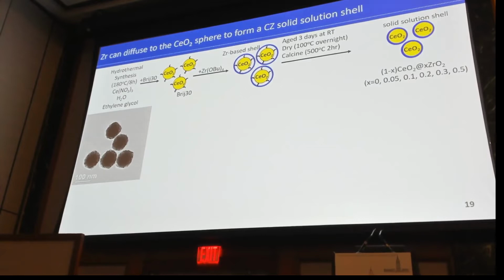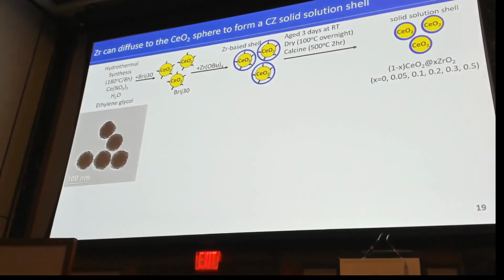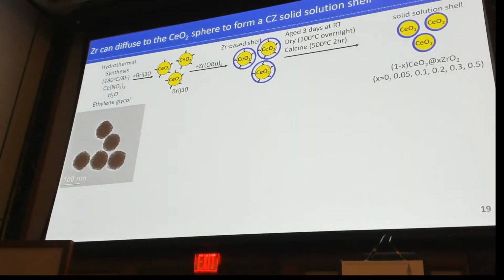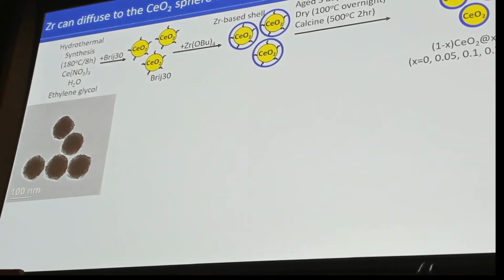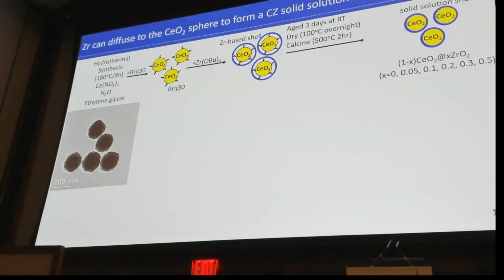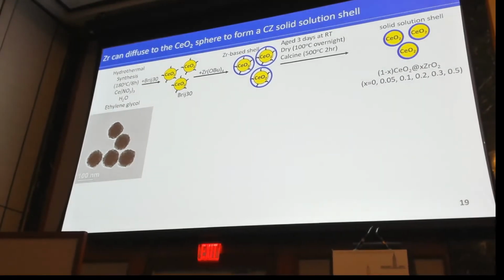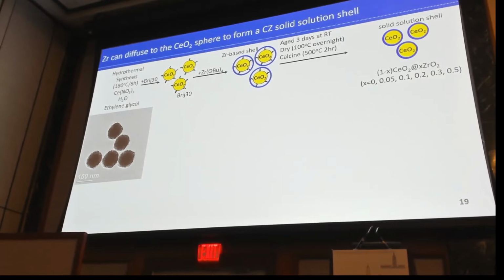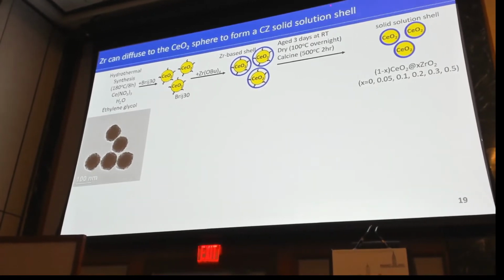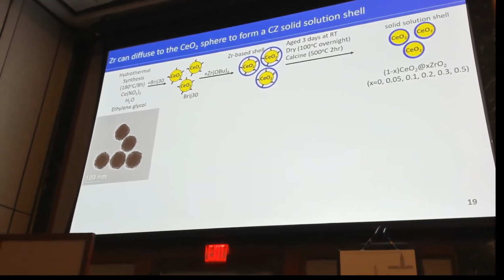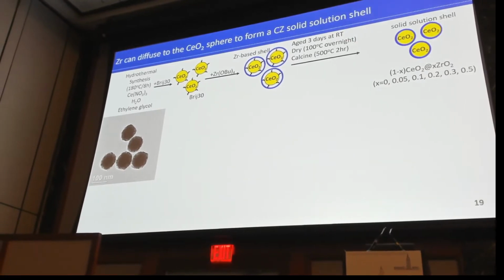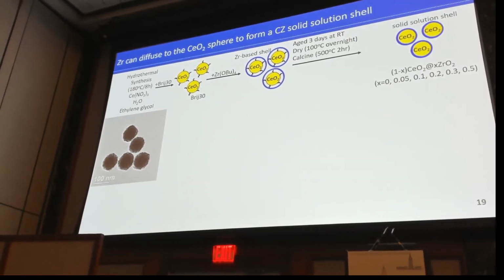Of course, we want to create a zirconium shell on this material, so we follow a similar process as in the first part of my talk. We add Brij 30, which is a surfactant, and zirconium butoxide, and then we allow the solution to age for 3 days at room temperature. Then eventually we collect the solid, we dry it at 100 degrees C overnight, and we calcine it at 500 degrees C for 2 hours. And we collected the material that you see here, and I'm going to show you the images to convince you that this is what we get.